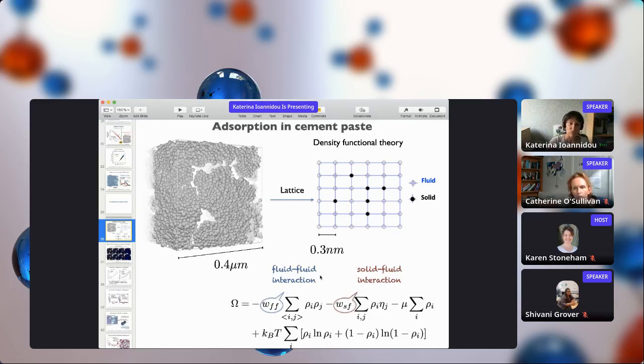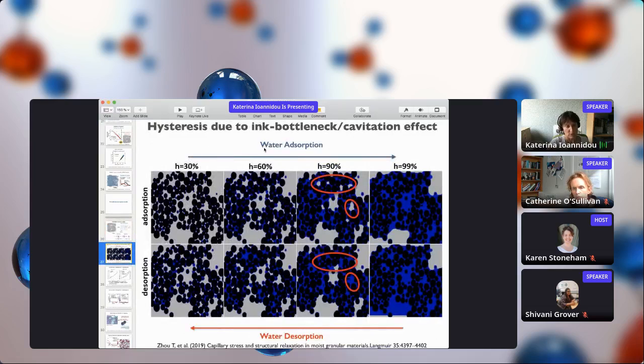We have used 2 different fluids: nitrogen, which is usually used to probe the pore space of cement, and water, which is very important because there is always water left in the pore space of cement. With this simulation, we were able to model the adsorption and desorption of cement. Here we see a slice of the system at different relative humidities of 30, 60, 90%. We see how the water is adsorbed around the grains, and we are going through all the different regimes: pendular, funicular regime, and fully saturated.